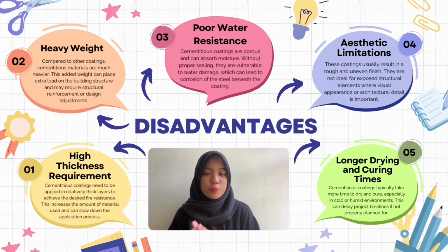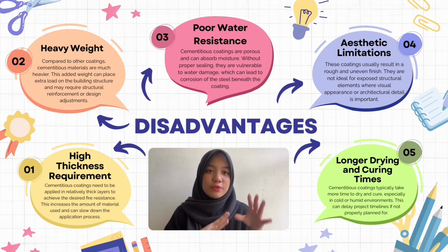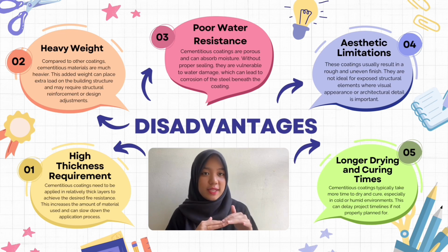Third, it has poor water resistance because the cementitious coatings can absorb moisture. If there is no proper sealing, they can easily be affected by the water, so it can cause damage, and if water gets in, the steel underneath might start to rust.